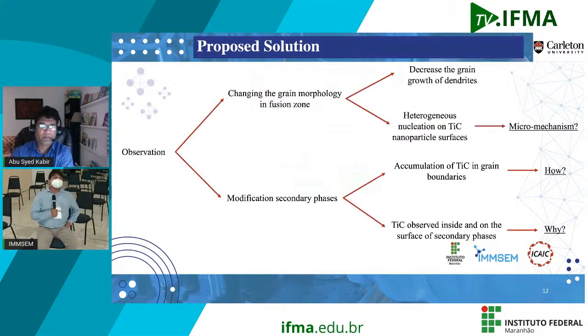So what was the proposed solution? What did really happen when you add titanium carbide nanoparticles in there? So according to that paper, what happens is that the grain morphology changes in the fusion zone, from columnar to equiaxed grain. And at the same time, there is some kind of modification in secondary phases as well.